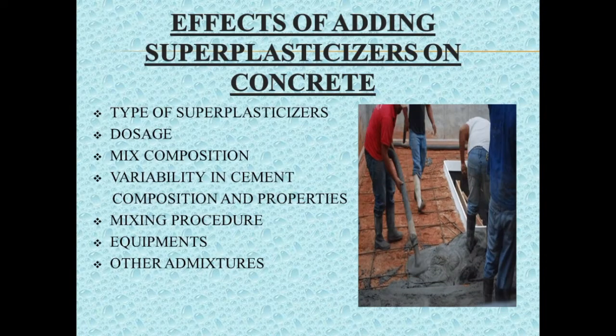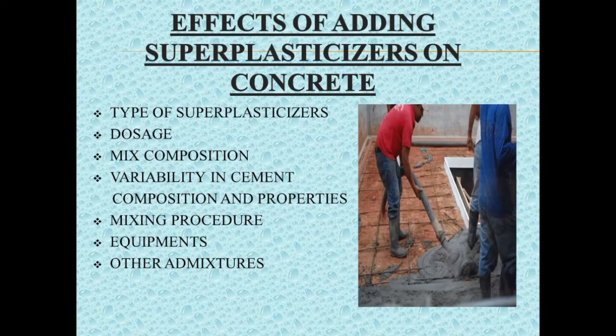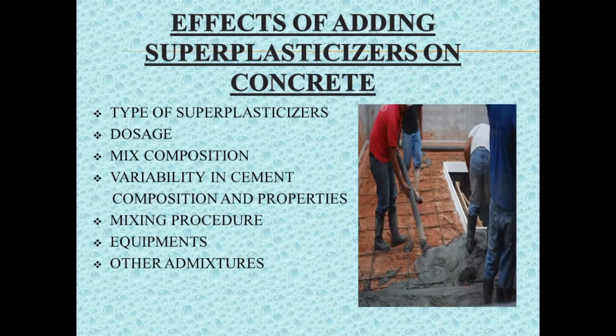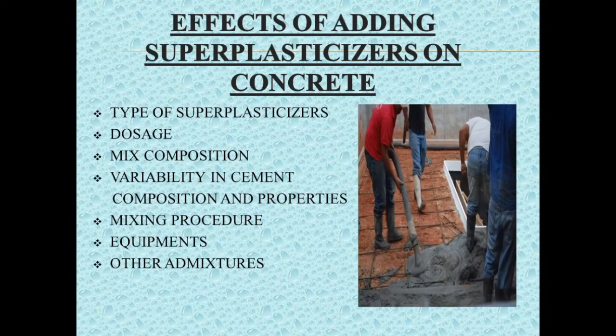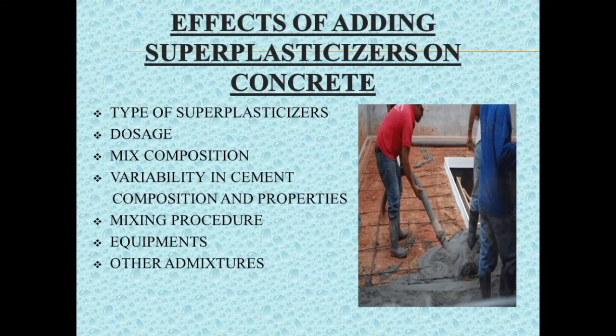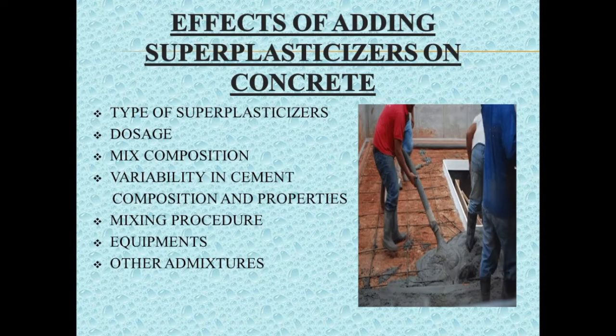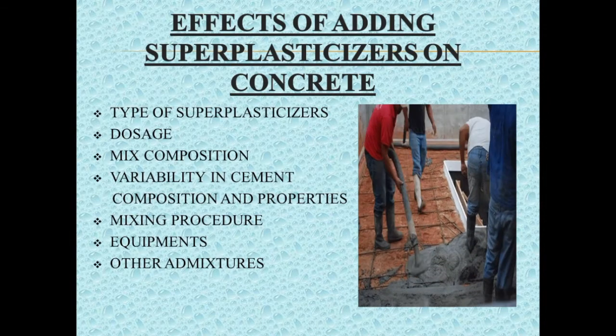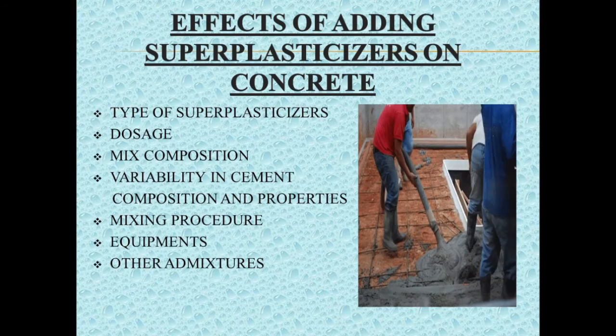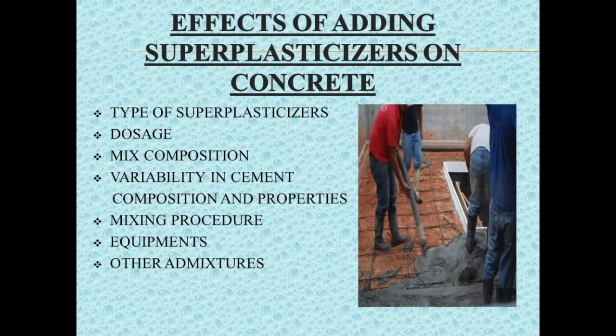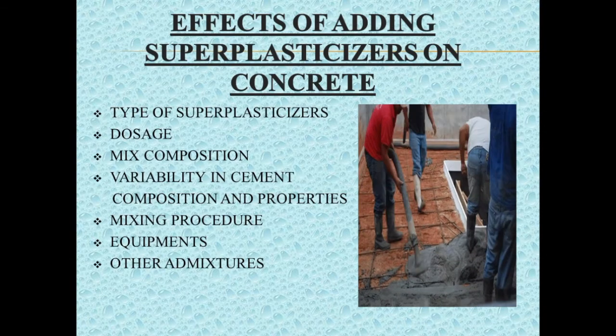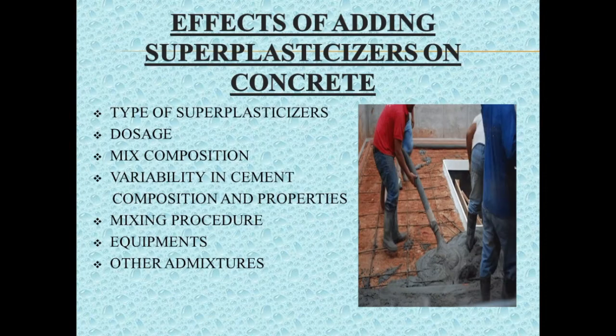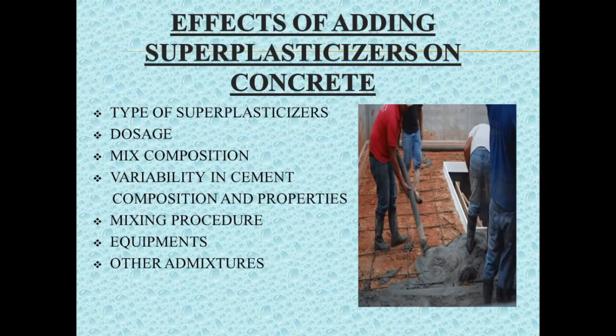The optimum dosage can be attained from the marsh cone test. Low dosage is adopted for normal concreting operations. Up to a dose of about 3% has no harmful effect on properties of concrete; however, higher dosage may result in shrinkage and creep.